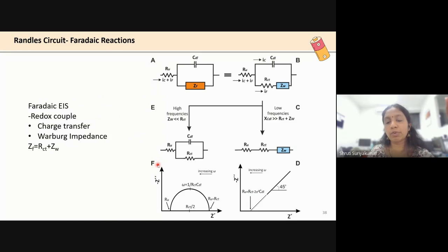And at higher frequencies, you're going to get a semicircle. So if you're plotting an impedance, when you start at high frequency and go toward lower frequency, this high frequency component will come first. So you have an RU. As many of you said, it's going to be a high frequency component. So you go from RU, then you get a semicircle, and you end at RU plus RCT. So this is going to be the point here on the real axis. And again, you will have a maximum point. From that maximum point, you can calculate the time constant, and it's going to be a semicircle. So this is how it is going to be at higher frequencies.